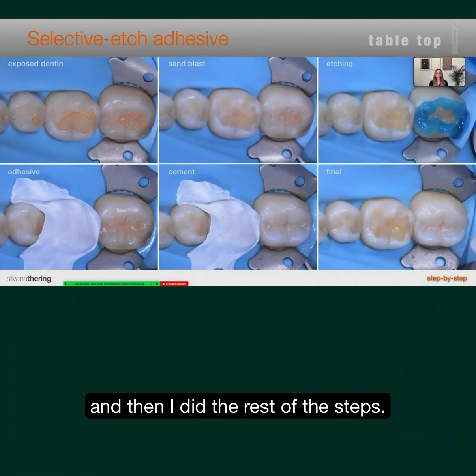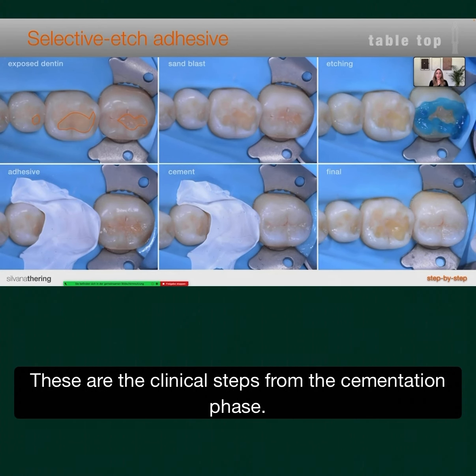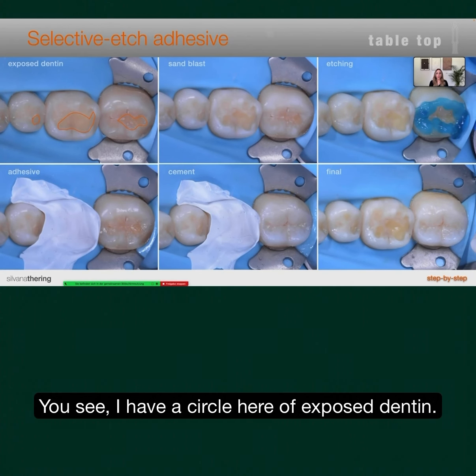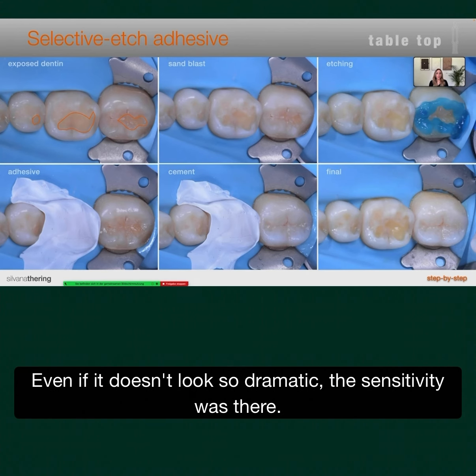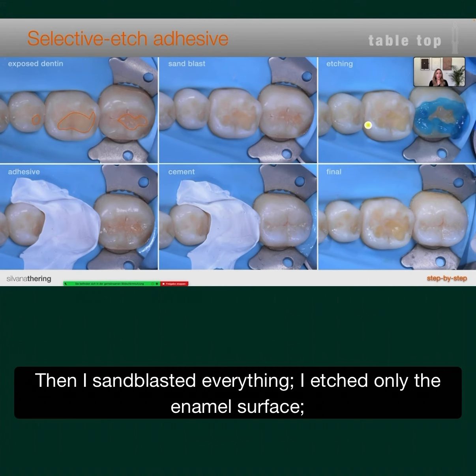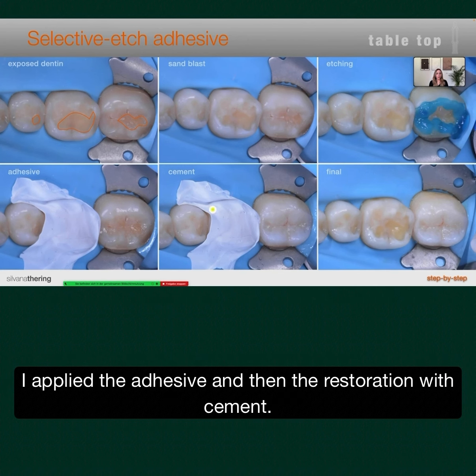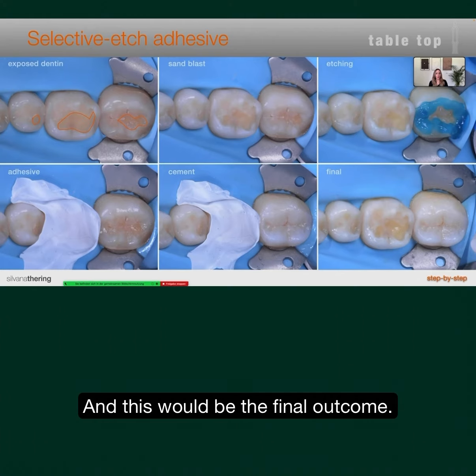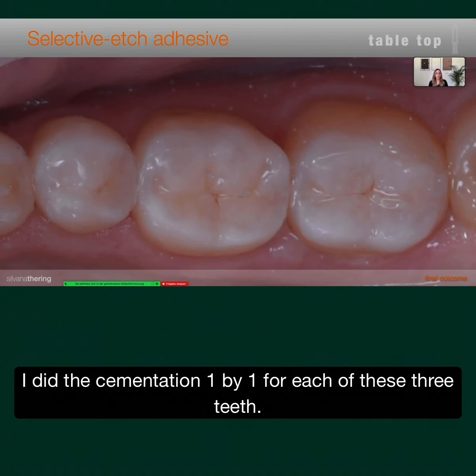I used a higher concentration of hydrofluoric acid for a longer time, and then I did the rest of the steps. These are the clinical steps from the cementation phase. You see I have circled here the exposed dentin. Even if it doesn't look so dramatic, the sensitivity was there. Then I sandblasted everything. I etched only the enamel surface. I applied the adhesive and then the restoration with cement. And this would be the final outcome. And I did the cementation one by one for every one of these 3 teeth.